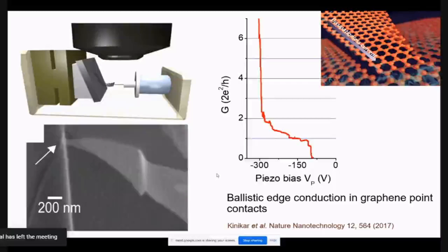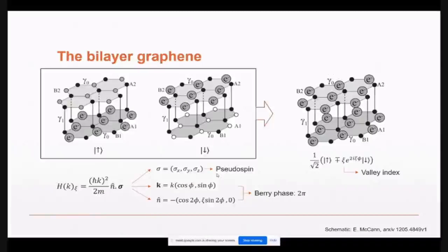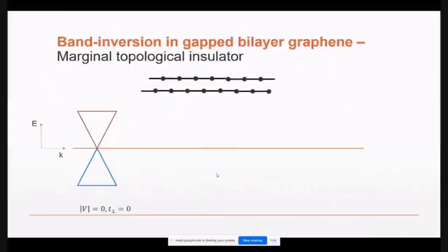Then bilayer graphene is very interesting as well, because here you have 4 electrons in a single unit cell, 2 from each layer, and that leads to, in the low energy band, a spinor type, with layer 1 and layer 2 acting as the spinor, like an equivalent spin. This is because of the interaction between the layers. You don't have the linear band structure anymore, but you have a parabolic band structure with a spinor. And that leads to something very interesting, to marginal topological insulator properties. I'll just give you a very brief look at how it looks.